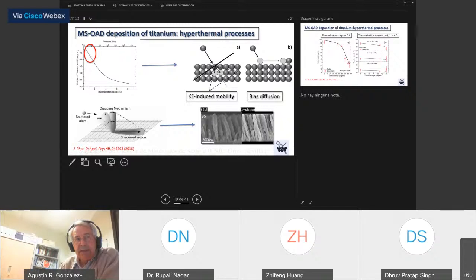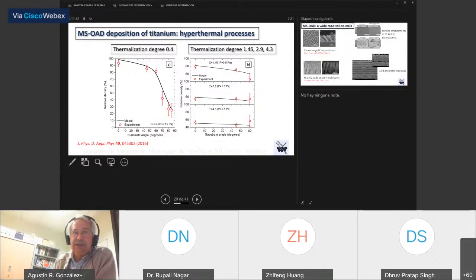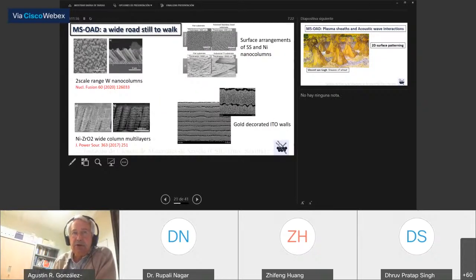What we have labeled this process as a kind of dragging mechanism in such a way that the energy and momentum brought by this sputtered atom arriving to the nanocolumns produce a certain increase in the upright direction of the nanocolumns. And also, as you can see here, a change in the width of the nanocolumns. Not only this change, also the density, for example, changes, and many other properties. The point that I would like to emphasize here is that playing with this other parameter that the magnetron sputtering situation offers makes it possible to control other features of the nanocolumnar structure typical of oblique angle deposition.